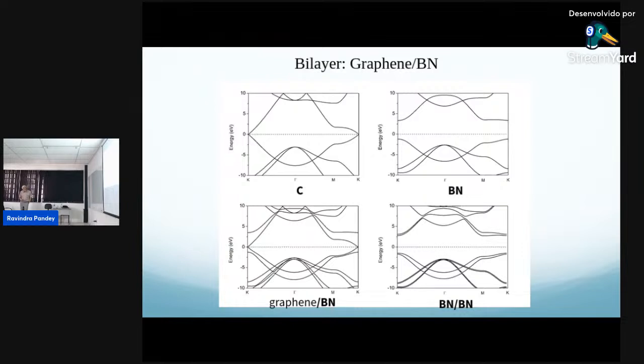The reason we picked the boron nitride bilayer is because it gives a reference point. Like in an experiment, when we do any experiment, you have to have the reference point. So we are trying to mimic the similar situation here. For graphene, you can see here, this is zero gap. The boron nitride has a very large gap, which you expect. Boron nitride bilayer, again, has more or less a large gap, for symmetry. And graphene boron nitride we see is some sort of similar behavior.